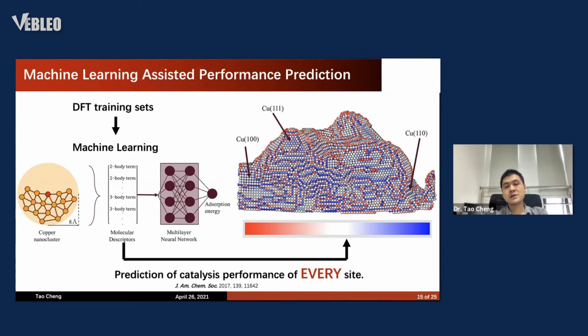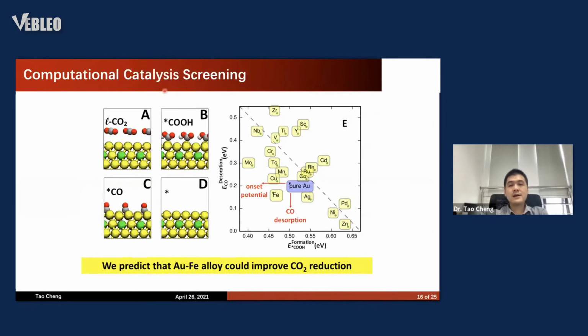than these expensive calculations. Here we show the cases where we can actually distinguish some really hot sites that can have high activities in these nanoparticles. And then we can also do predictions. We can computationally screen materials that we can propose for the experimental people to synthesize. Here we show a case, the gold nanoparticle.